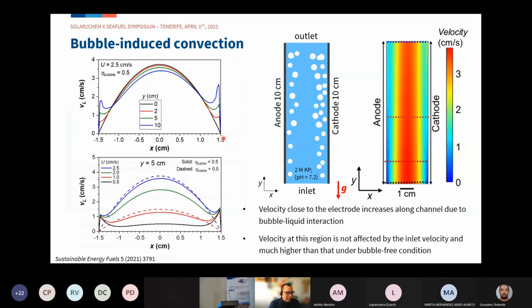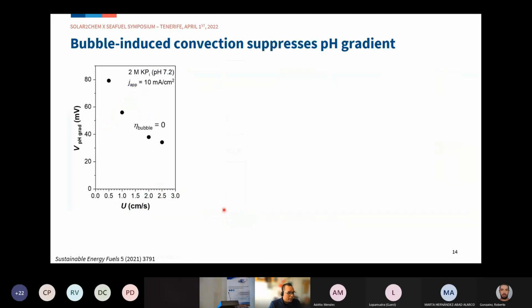The velocity at this region turns out to be not affected by the inlet velocity, i.e., this bubble-liquid interaction is the dominant factor causing the velocity at this region. This is of course important because again, this is where the pH gradient is formed.